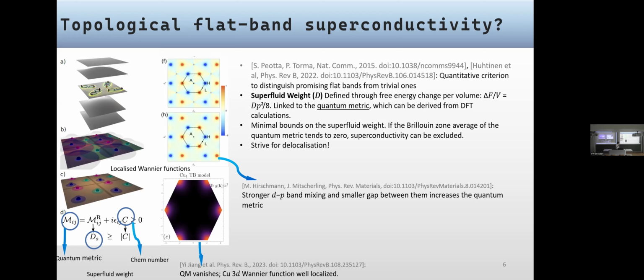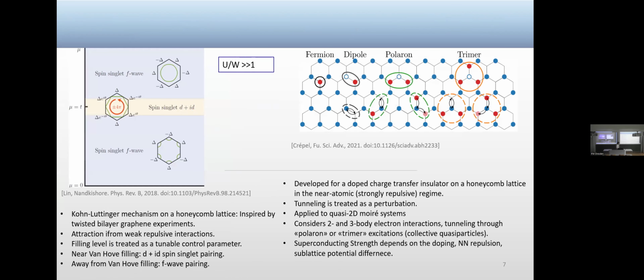Also I need to show the band structure as well, but the thing is that oxygen and copper orbitals come very close to each other, and if touching occurs, then it's also beneficial. Anyway, the idea with this topological non-triviality is also linked to the real space localization of the orbitals, meaning that if they are very well spatially localized, then it's more likely to be trivial than not. Right.